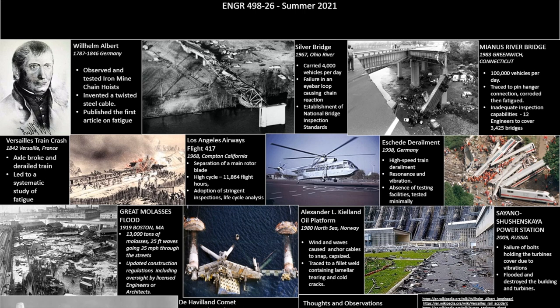The Silver Bridge, shown in the middle, failed in 1967 over the Ohio River. The bridge spanned the Ohio River, carrying 4,000 vehicles per day. Failure was traced to a small fatigue crack in an eyebar loop, which caused a chain reaction failure. This has spurred the establishment of the National Bridge Inspection Standards.